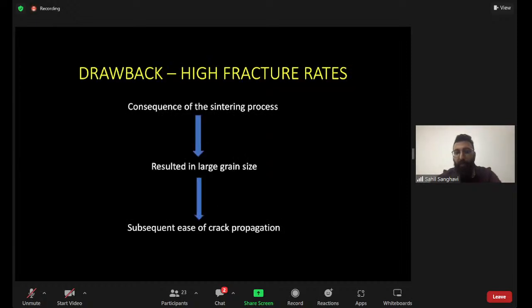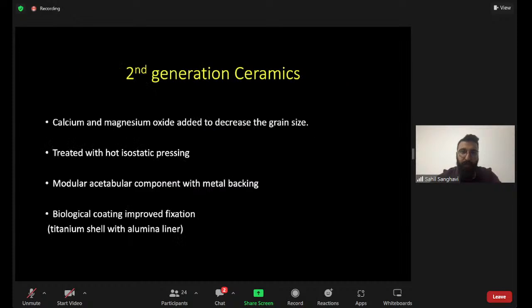So the drawback again was high fracture rates. And this was mainly a consequence of the sintering process, which resulted in large grain size. This large grain size caused subsequent ease of crack propagation, leading to ceramic fractures. So in the second generation ceramics, there was an effort to decrease the grain size by adding calcium and magnesium oxide. So these were treated with hot isostatic pressing, and you had modular acetabular components with metal backing.